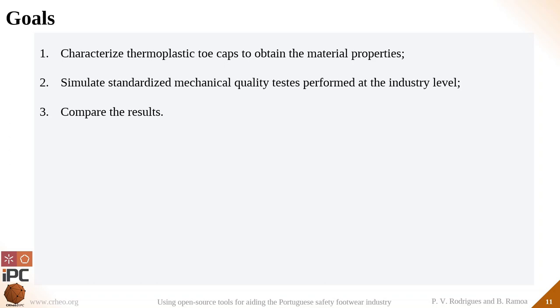So for this project, we were approached by a company partner that wanted to identify and model the mechanical performance of a commercial plastic toe cap. And therefore, our main goals were to identify the toe cap materials and characterize the material of the toe cap in terms of mechanical performance through a tensile test, model the standardized tests for safety toe caps, which are the compression and the impact tests, and finally compare the simulation results to the experimental results and try to validate the tool.